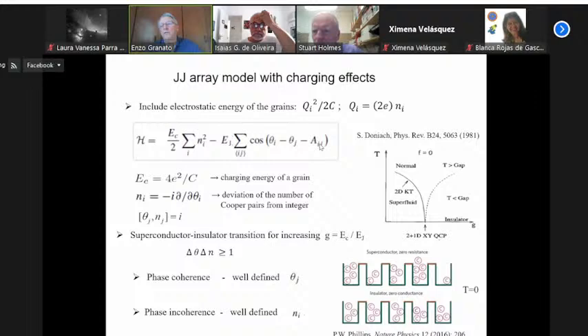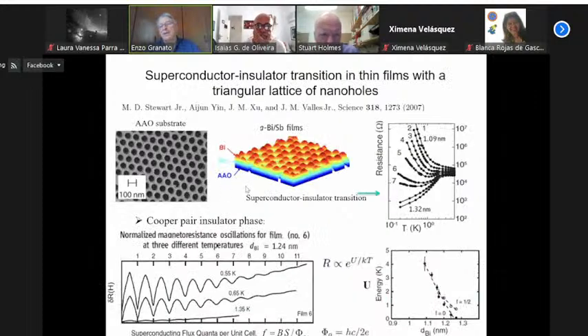if there is no magnetic field, then all the phases are uniform and you get superconductor. But then if you take into account the charging energy of the grains, then eventually this term dominates over the other one because you increase the EC. And that's why you get this superconductor-insulator transition. The interesting aspect of this particular system is that there's a question if the superconductor-insulator transition in any of the systems that you see, films for example, can be described just by a bosonic model, in which you only consider bosons which are superconducting and then become localized, like with hopping that you said, or there is a Mott gap or something like that. And there's another possibility that the transition is actually due to free electron localization. And so this is difficult to distinguish experimentally.